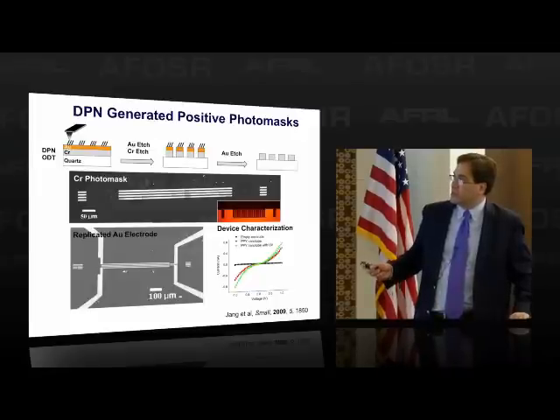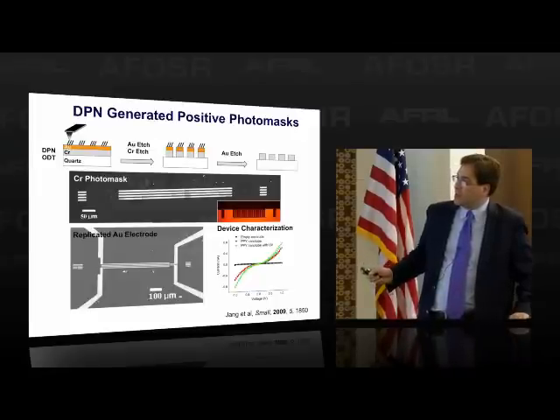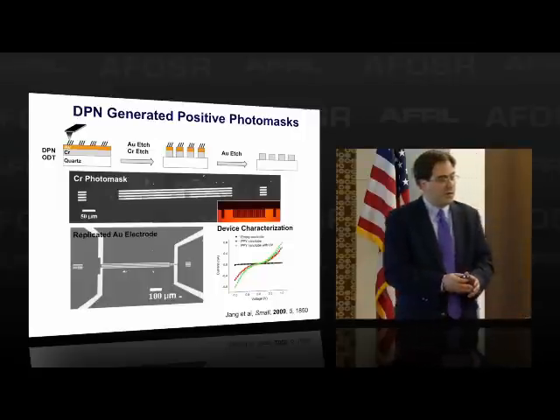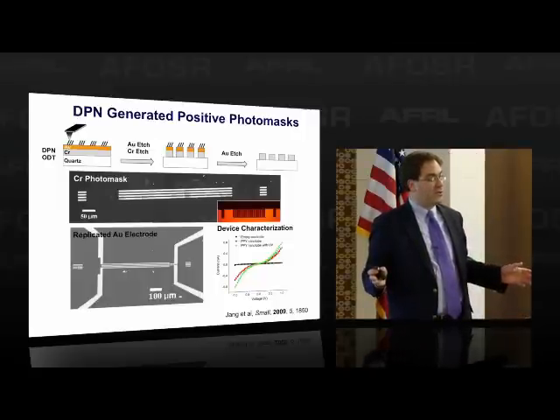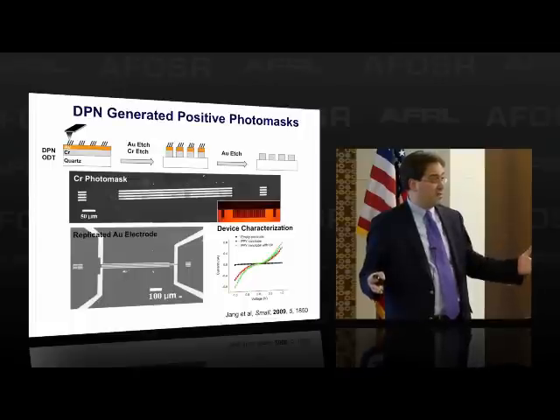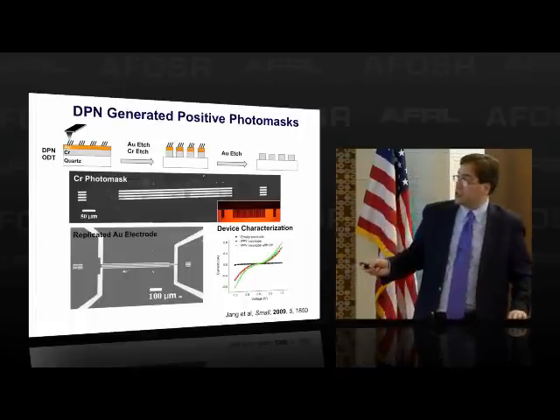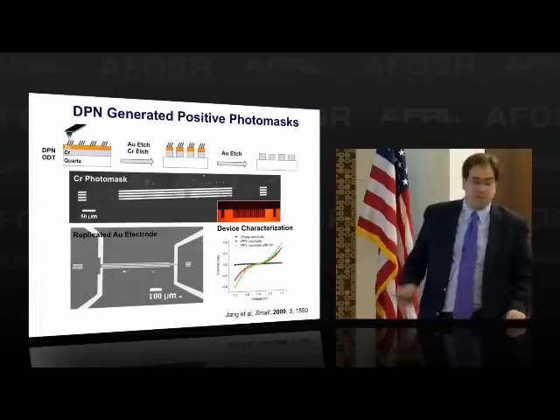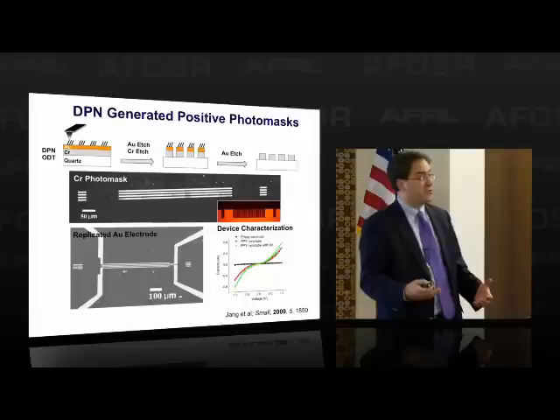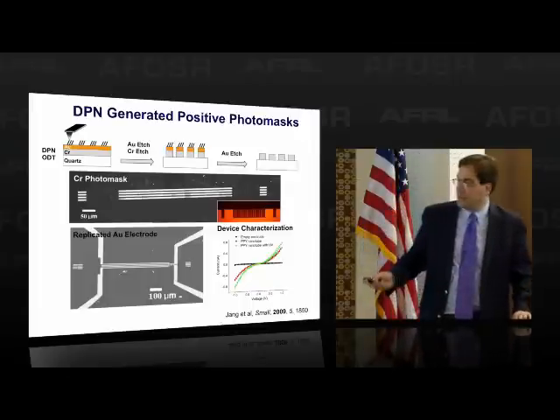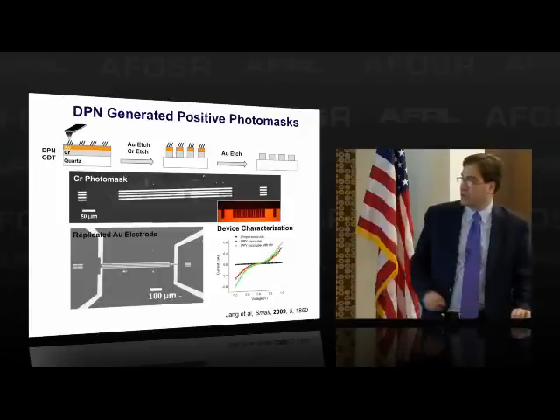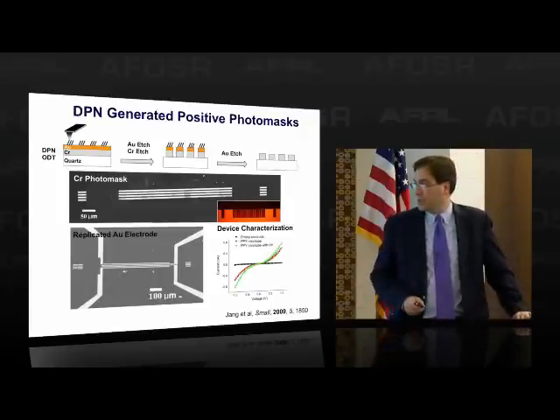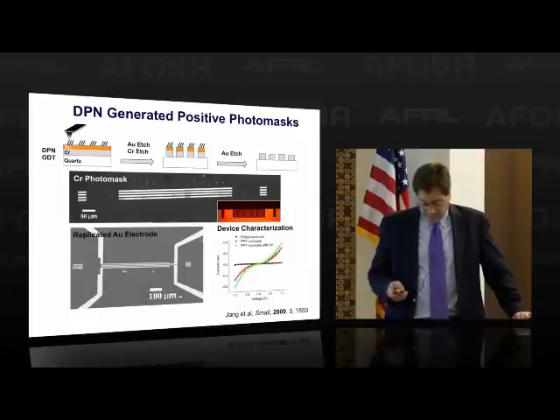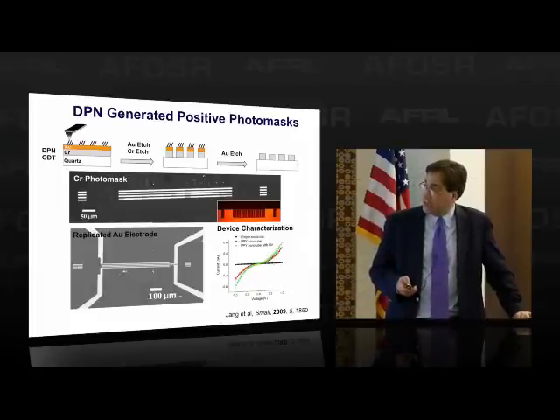And the point is, this can now be made. We've actually created linear arrays like the one shown here, where you can duplicate the number of pens that are being used, so you can increase the throughput by the number of pens that are used in the array and stitch the structure together. But then you can use these types of photomasks to literally produce interdigitated electrode devices. And these are some of the devices that have been made, and here we're making measurements on polypyrrole coated nanotube structures. So that tells you that these are in fact functional devices as well, not just fancy images.